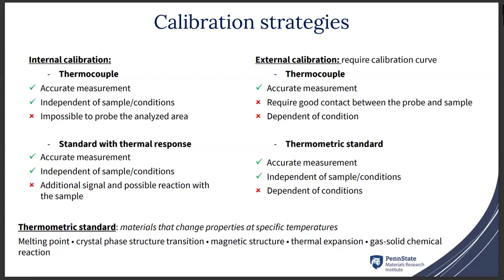The second and most widely used method to calibrate those accessories is external calibration. So either using a thermocouple, which gives you an accurate measurement - you put the thermocouple where you're doing the analysis, you cannot do it at the same time, and you create a calibration curve, then you assume that for your material, you have the same temperature profile.